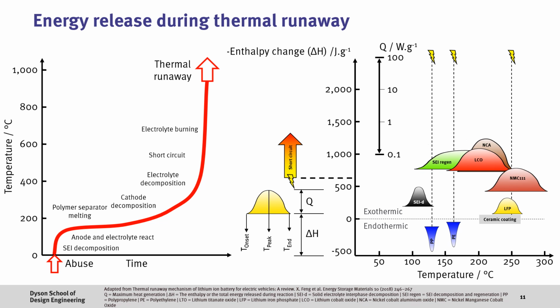Then we have LFP or lithium iron phosphate, which has in recent years seen renewed interest due to the low-cost nature of iron, but also because of its safety characteristics. Here you can see LFP has both a high onset temperature, but also a low heat release rate and total heat energy, which makes it much safer. Finally, we have the highly exothermic process associated with the graphite and electrolyte decomposition, which ultimately leads to the combustion of the entire battery, which is the worst case scenario.